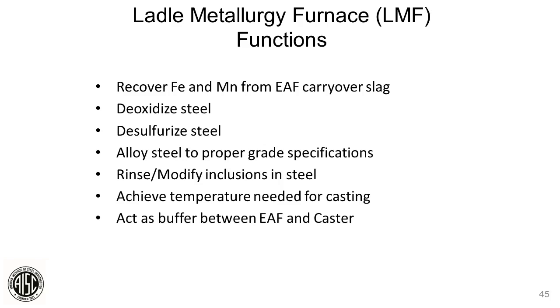Our job is now to deoxidize the steel. Like I talked about before, the EAF is an oxidizing environment. The LMF is a deoxidizing environment. Once we have the heat killed, we now desulfurize the steel. We're going to alloy the steel to the proper grade spec. We're going to rinse it through the porous plug, argon stirring on the bottom of the ladle, and modify the inclusions of the steel, achieve the temperature needed for casting, and act as a buffer between the EAF and the caster. Next slide, please.